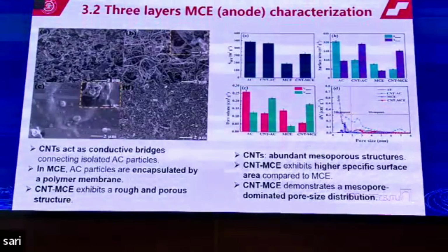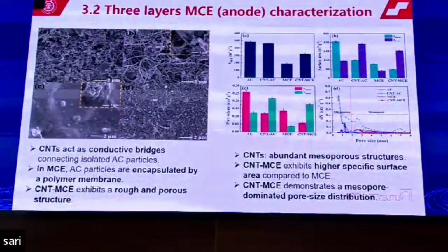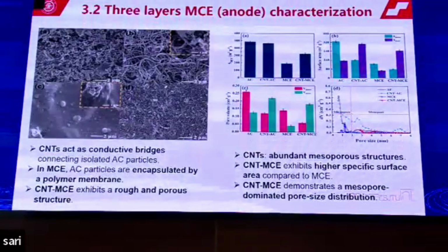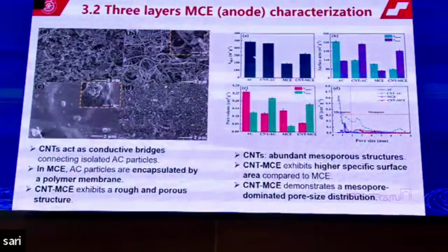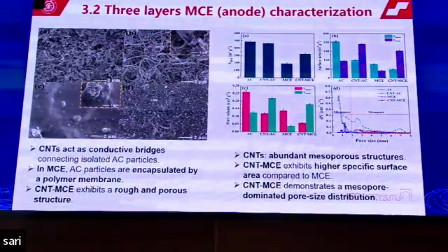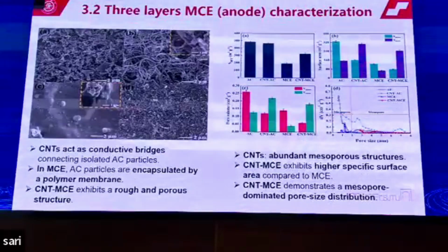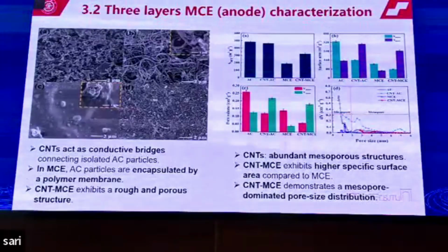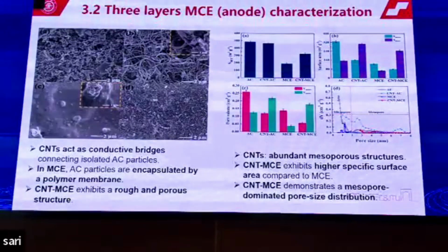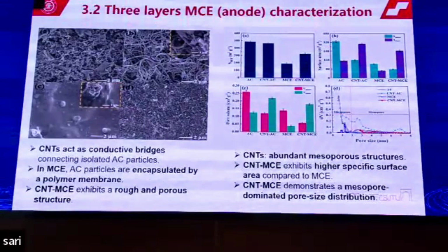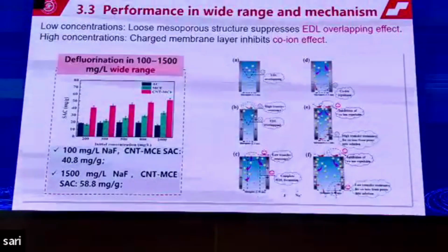Besides, after the addition of the CNT as an interlayer, the formed CNT and MCE showed a rougher and more porous structure. From the further BET result, we can see that even though the CNT MCE was a little lower than the AC, the increase of it was more obvious than the MCE. Especially, it showed a more mesopore-dominant structure. Then we use it for the